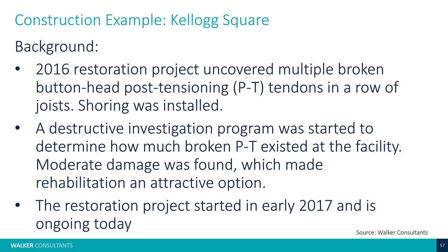And we started opening those up, and we found quite a bit. So we said, all right, let's extend this program. Let's look at other areas that are in good condition as well as areas that are in bad condition so we can give a fair assessment to this owner, instead of just looking at the worst case scenario throughout, in terms of what repair costs we're actually looking at. So we did the destructive investigation program. What we found was, yeah, there's a bunch of broken post tensioning in here. However, the cost of replacement versus cost of rehab was way different. So it was going to be much cheaper to rehab this building in place than to replace it.